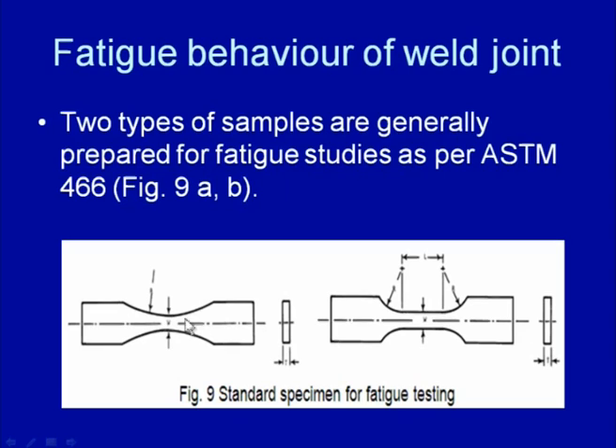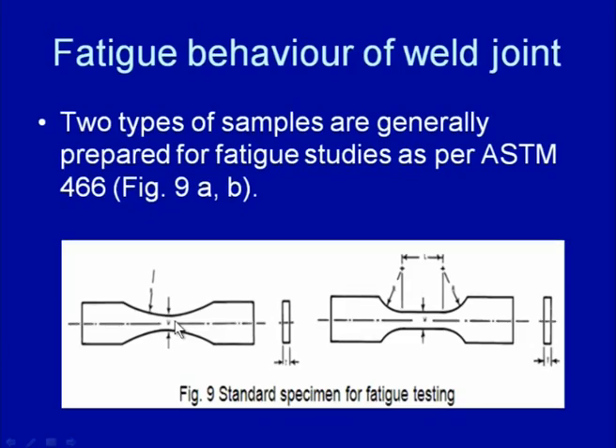One is this reducing radius sample, where the cross section of the specimen is reduced gradually, and this is another kind of sample which is used for fatigue testing. In the first case, the reducing radius specimen, the stresses are always localized in the minimum cross-sectional area zone, and this is mostly kept in the weld region. So, it helps to assess the fatigue performance of the weld joint itself.